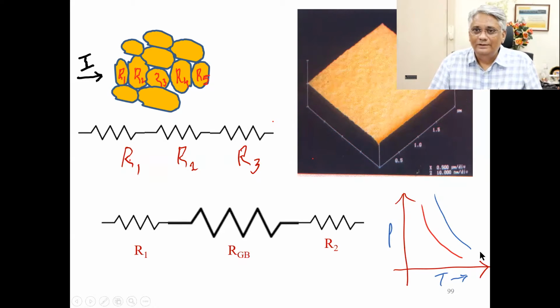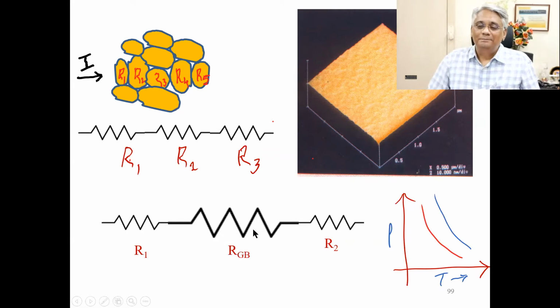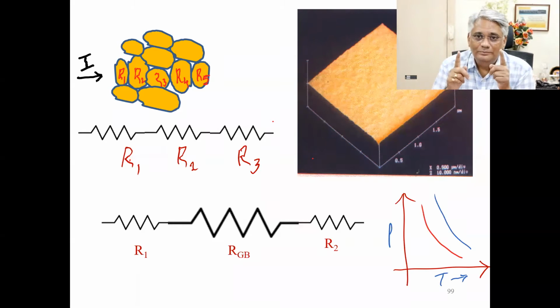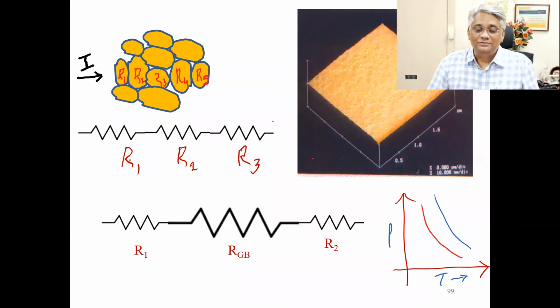Now, rho versus T for a semiconducting material, you measure it in the thin film form, crystalline form, and a bulk form. Now you can find out which belongs to the single crystalline form and which belongs to the bulk form. And obviously, the one with the polycrystalline nature shows more resistance because of the inclusion of the grain boundary resistance. You see how nicely a physical property is correlated with the microstructure. There's always a correlation between physical property and microstructure. So the structure property correlation is extremely important.